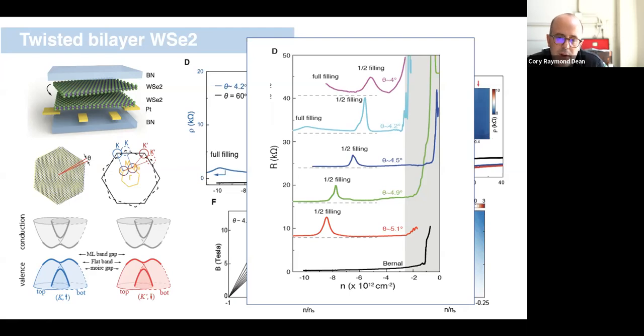And as we increase the twist angle, that corresponds to a decreasing of the Moiré wavelength. And as one expects, the half band filling point for smaller wavelength requires more density of holes to reach 1 hole per unit Moiré cell. That shifts to higher and higher density, just as expected.